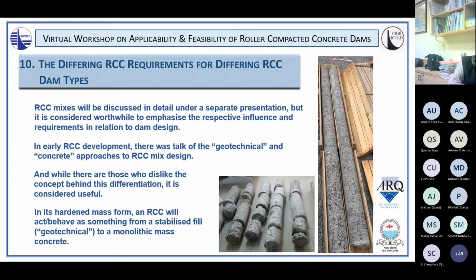And in its hardened mass form, an RCC will act as something between a stabilized fill, from the geotechnical point of view, all the way to an absolute solid monolithic concrete. So these options exist from one all the way to the other in RCC. We're not restricted. There isn't one solution. There's not one just weaker or stronger type of concrete. We have a completely different system of concrete with, as I say, at the lower cementitious end, something more like a stabilized fill where we have heterogeneous layer profiles and all this sort of thing, all the way to a very, very homogeneous and solid concrete where you cannot really differentiate any weaknesses between layers, etc.